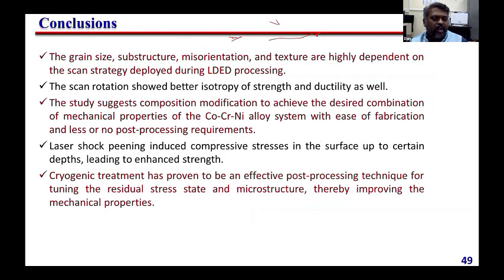So overall, what we understood is that initially when we are doing deposition, the grain structure is different and it is also forming a preferred kind of texture. But when we change the scan strategy, it gives better results than the as-deposited sample. As compared to the 0 degree scan rotation, 67 and 90 both give better properties, and 67 gives better isotropy in strength and ductility. That's what we understood. And when we change the composition, we got different phases. That also we understood from this study.